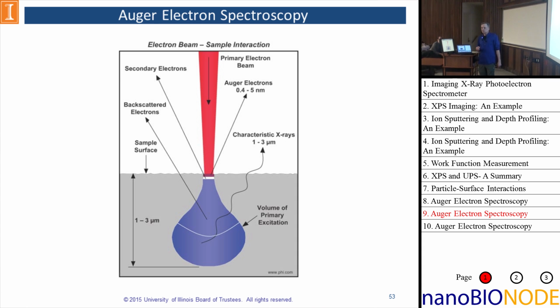As I mentioned earlier in this morning's talk, Auger Electron Spectroscopy is a technique where we're looking at electrons, so it is very surface sensitive, and we'll be concentrating on these electrons here. Because we're very close to the surface in this area, near the neck of the bottle, our analysis area is pretty comparable to the probe dimensions. So we'll get roughly half micron lateral resolutions.